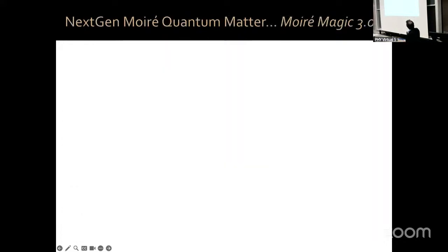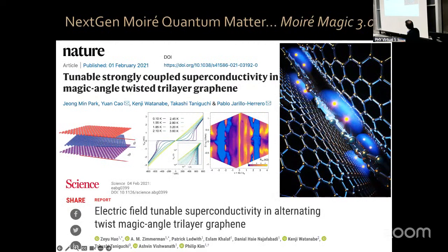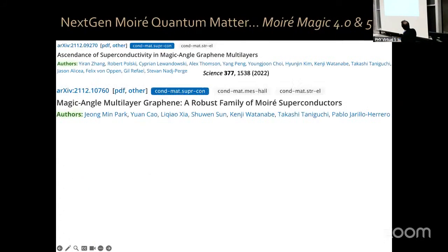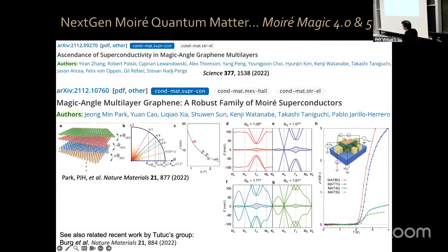In my group, and also in the group of Philip Kim, a few years ago we discovered tunable strongly correlated superconductivity in magic angle twisted tri-layer graphene, where you have three layers twisted at a different magic angle. The following year, three groups, including mine, discovered that magic angle tetralayer and magic angle pentalayer graphene, again with different magic angles for each condition, are also superconductors. So we now have this magic angle multilayer family as a robust family of Moire superconductors—not just twisted bilayer graphene, but an entire family with different numbers of layers.